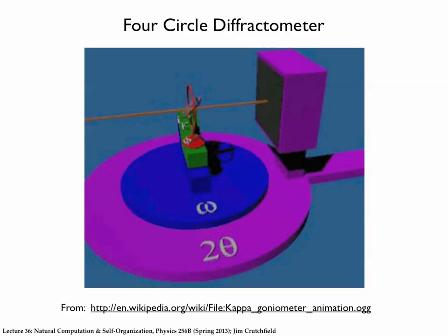Now, it turns out that diffraction, because it's adding up wave magnitudes, is a power spectrum. I don't want to prove that to you, I hope you'll just believe me, but it's exactly the same kind of power spectrum that we talked about last time. It is mathematically no different, except now there are going to be some subtleties. Remember translating the language going from 0-1 to 0-1? What that means is that we're going to want to think of each layer in the crystal being either A, B, or C as coming from an alphabet, and think of those as a symbol sequence in space.